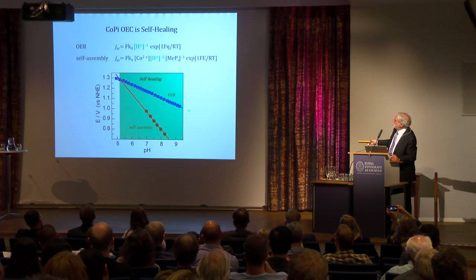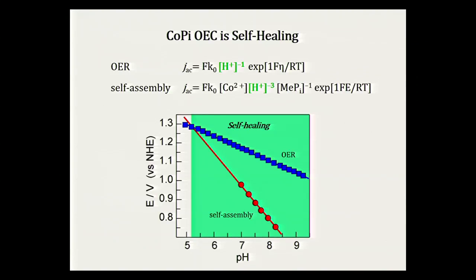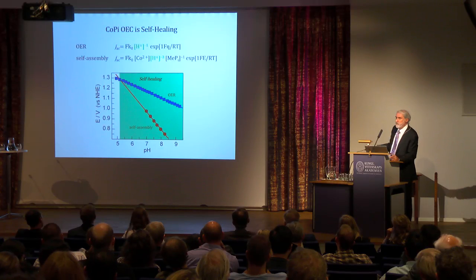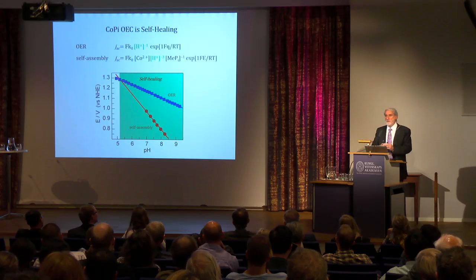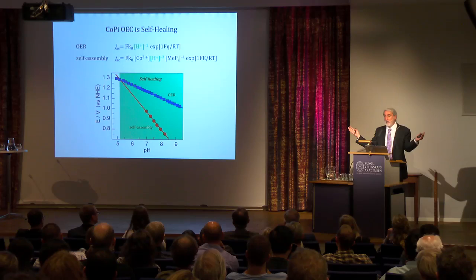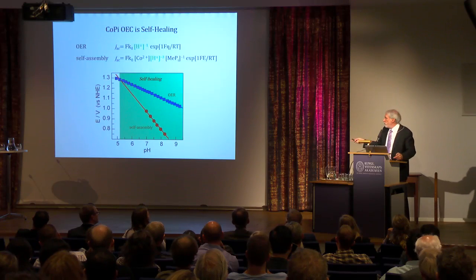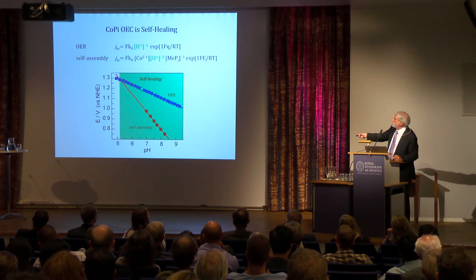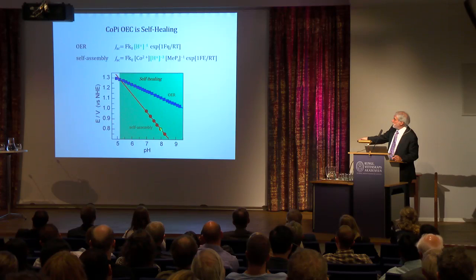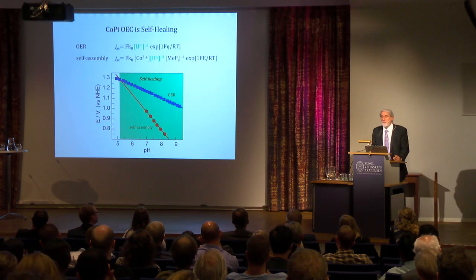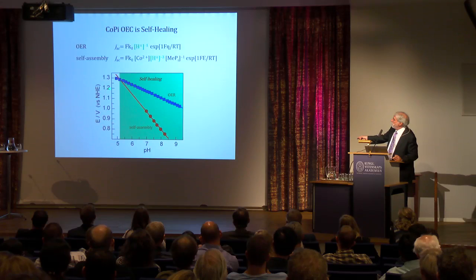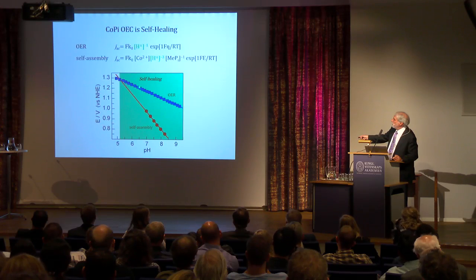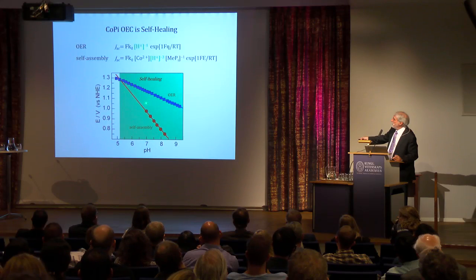Because here, this blue line right here is the catalyst making oxygen. And so if I'm at pH 7, at a voltage of 1.2 volts, you need 1.23 volts to split water to oxygen and hydrogen. So at 1.2 volts, the catalyst is making oxygen. This red line is the curve for self-assembly. And so what you find out is if I have a voltage of 1.2 where I'm splitting oxygen, I have plenty of extra voltage.